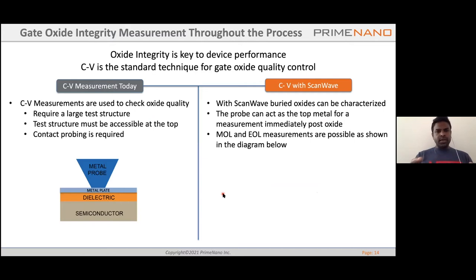And then I want to talk about the applications where ScanWave has been very useful. To start with, I'd like to talk about the measurements of gate oxide integrity and how it's traditionally done. On the left, we have how you look at the CV measurements today using a nanoprober kind of technique, wherein you have a large metal plane. The probe is also usually larger, and you look at the capacitance response as you ramp the bias. This usually requires a larger test structure, from a device perspective, and this must be accessible so that the probe can actually be in contact with the metal.